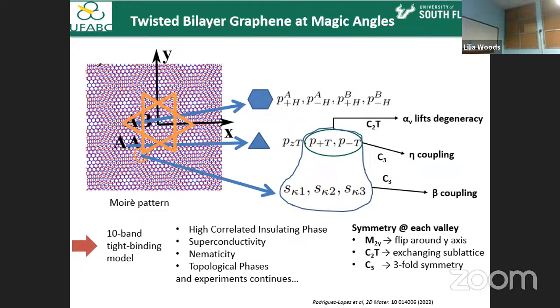Each one of these parameters is going to control a particular type of symmetry. If we follow Professor MacDonald's idea that, because of the competing effects in strong correlation that occur, these competing effects have symmetries that are being broken simultaneously. I change my substrate, or maybe I change the Fermi level by applying a little bit of field. Every time I tilt one of the symmetries somehow, I cannot model this from first principles, but I can mimic what happens in the lab by introducing these parameters. This is what we've done.